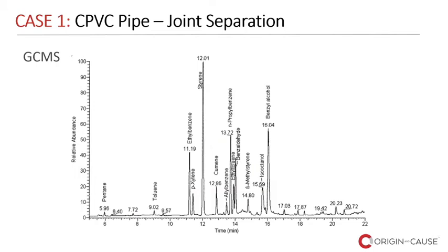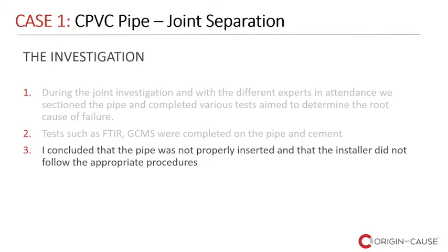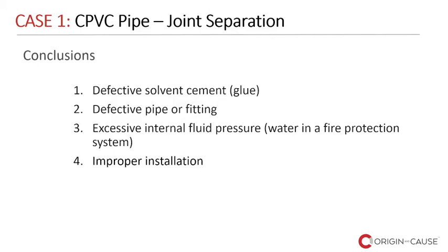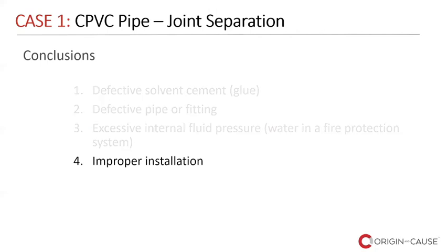to identify specific components, and the quantity of those, that can be detrimental to the materials, or in this case, the contact cement. In this case, we did not find any components or deviations that were large enough to support a hypothesis of the contact cement being defective. But we did find a lot of issues with the insertion depth and the cutting of the pipe, and all of that together led us to conclude that the installation itself was the only contributing factor to the failure, that the installer did not follow the appropriate procedures, and as such, the improper installation was the cause of this loss.